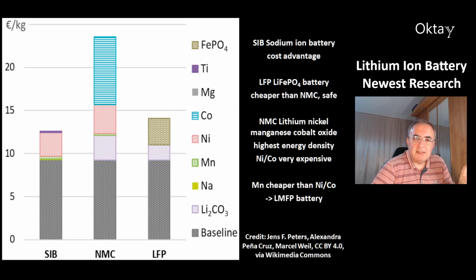At the right, that's the LFP battery, lithium iron phosphate battery. Here you can see one part is the iron phosphate. That's the lithium. And this LFP battery is cheaper than the NMC battery, and it is safer. And you can see a very interesting thing, that's manganese. Here is a very low percentage of the costs. So in the future, the LFP battery could be improved to the LMFP battery, which is a lithium manganese iron phosphate battery. And this would give you a bit higher energy density.